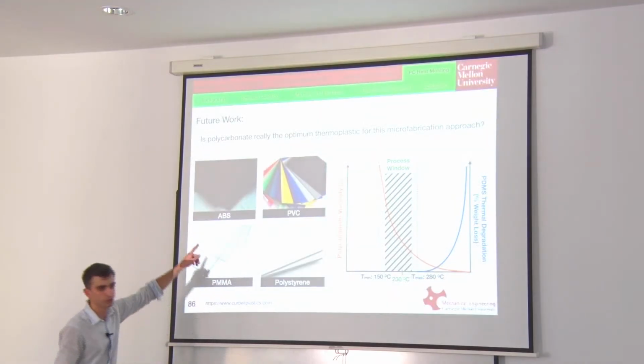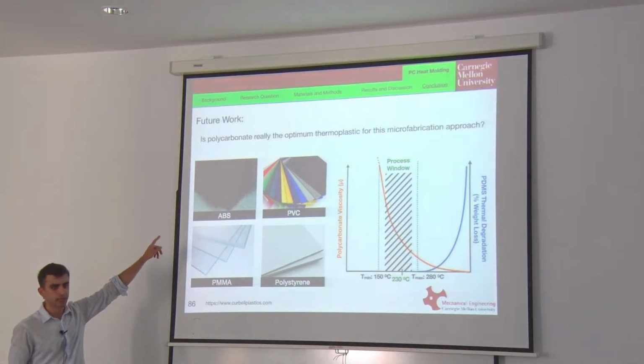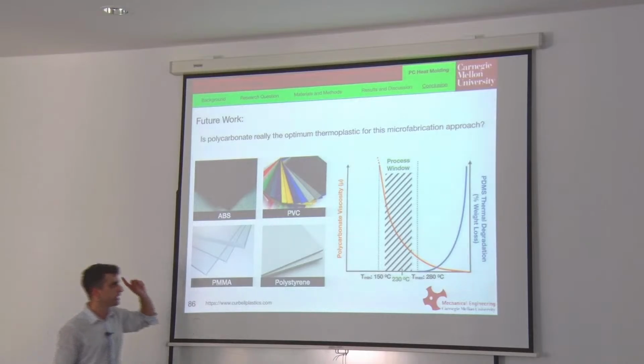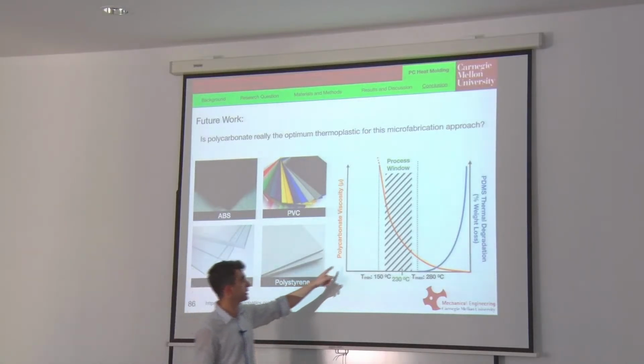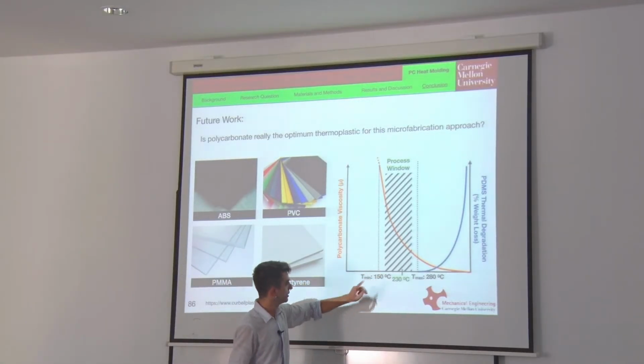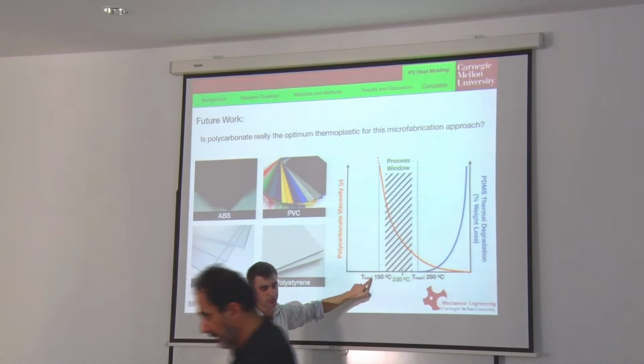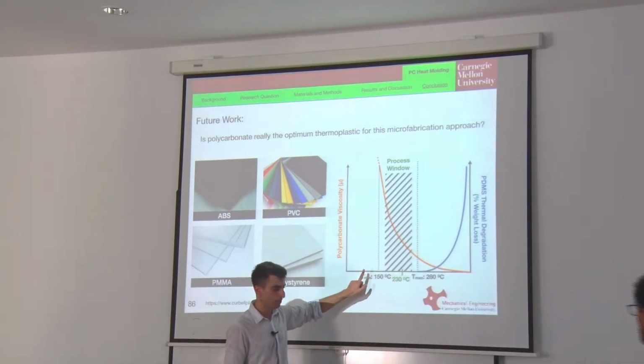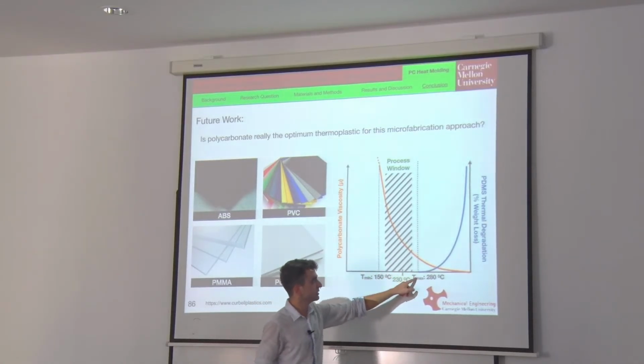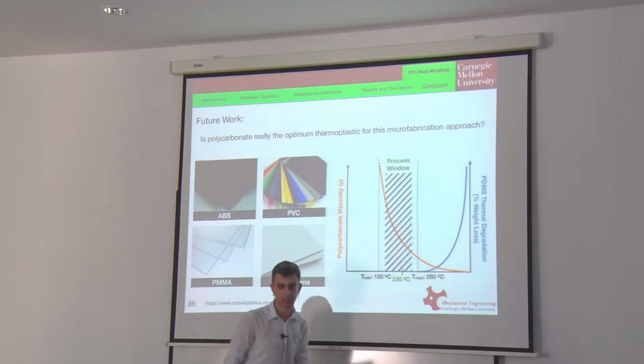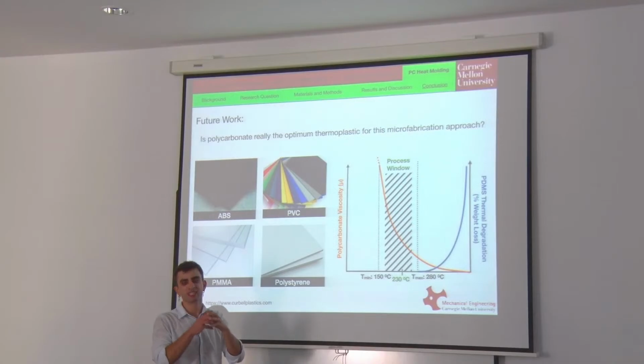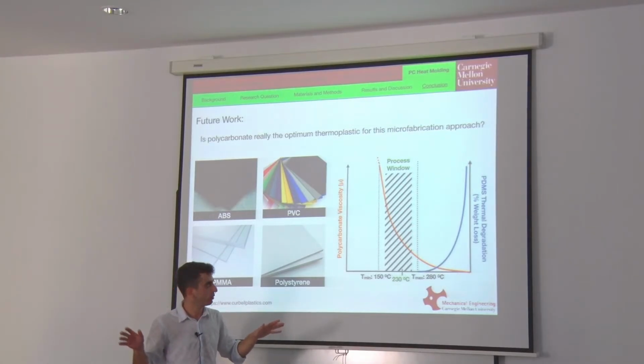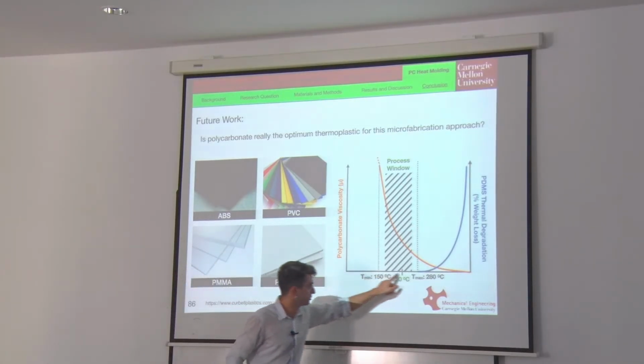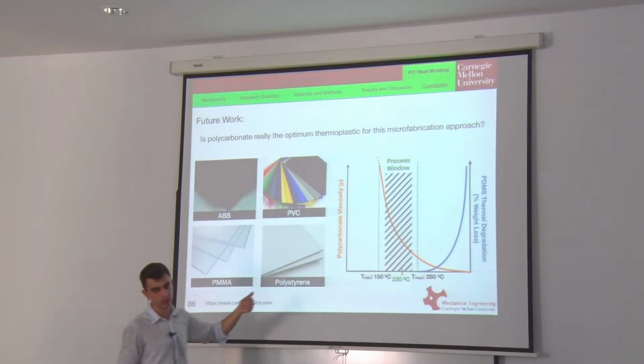So there are lots of different material options that you can use. They should be able to fit this process window. This is the glass transition temperature of the specific thermoplastic material that you use, and this is the thermal degradation temperature of PDMS. If you go beyond 280 Celsius when you are heating up, the PDMS starts degrading, so you lose all the microtopology. So as long as it fits this process window, you can use different ones.